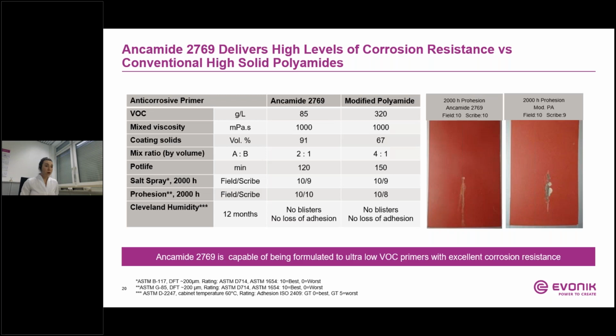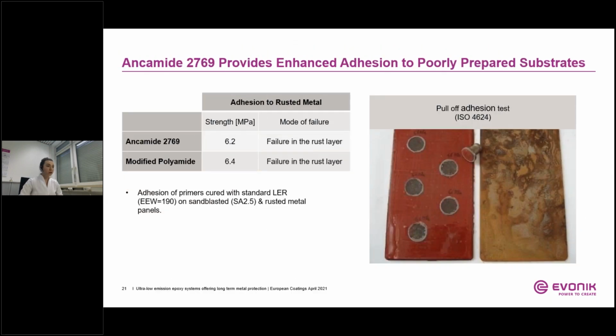So here anti-corrosive primer formulation based on 2769 exhibit excellent corrosion resistance with minimal or no failures up to 2000 hours in salt spray and corrosion test. As you can see on the table, the results for Ancamide 2769 are in line with competitive system, where we can achieve highest rating for creep and field blistering. Anti-corrosive formulation based on Ancamide 2769 show also very good adhesion on poorly prepared rusted substrates, where the pull-off test we performed indicates 6 megapascal strength.